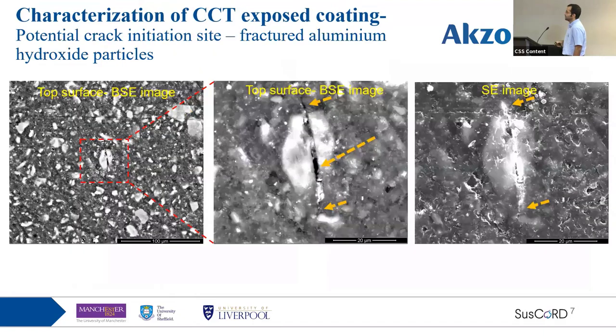The other place that we observed is that these seed particles are breaking, and there are breaks within the coatings. Also during the cyclic corrosion test, we had cracks within the particles. So those also may lead to the fracturing of these particles. But as is evident here, we have a fractured particle, and it looks like the crack has started to propagate from this fractured particle into the coating. So this is the second initiation site that may exist there.